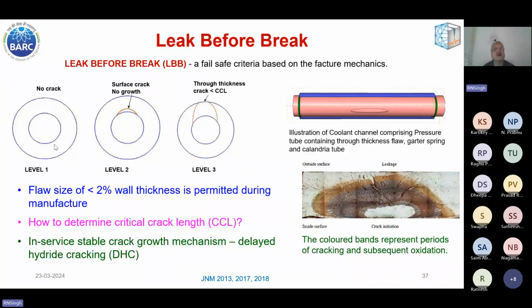So level 2 assumes the presence of a surface crack, but we assume that there is no growth of the crack. However, as we have seen, under operating conditions delayed hydride cracking can occur, and that can result in crack growth. So level 3 assumes a crack, but assumes that the leak size crack should not be more than the critical crack length. So a flaw size of less than 2% wall thickness is permitted during manufacturing. And with this we determine the CCL by estimating the crack driving force under the operating condition.